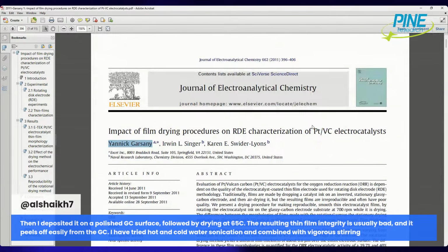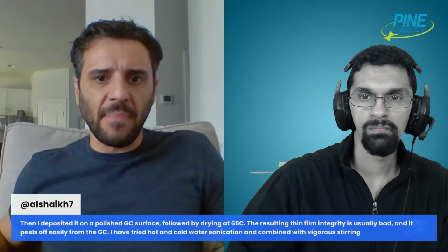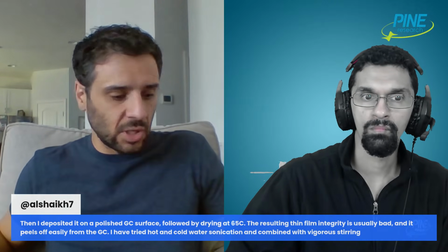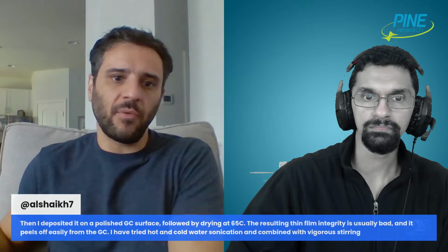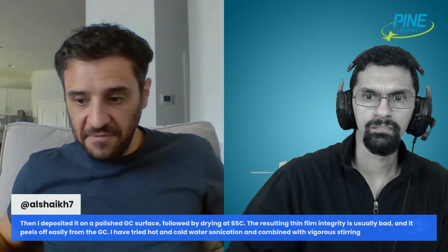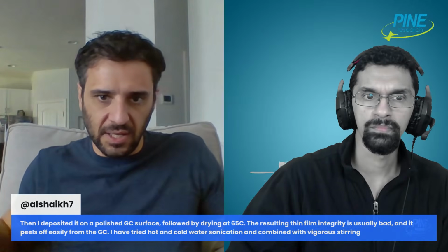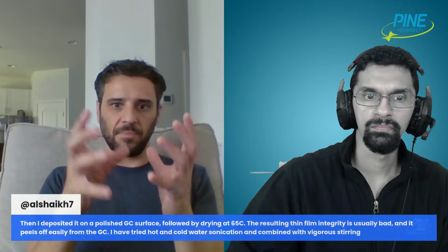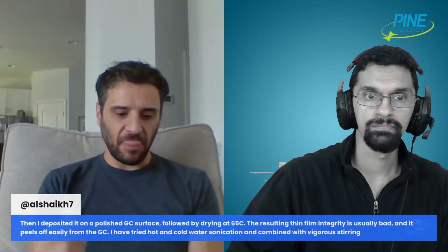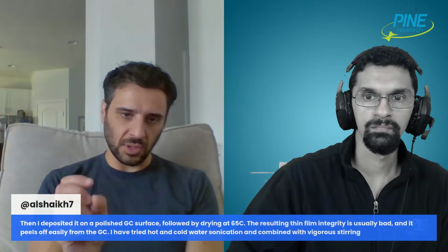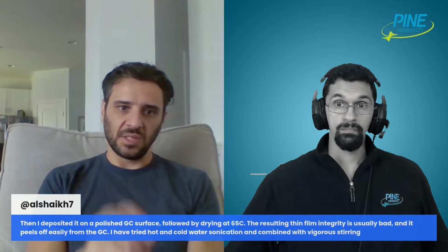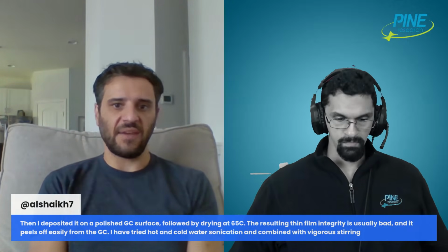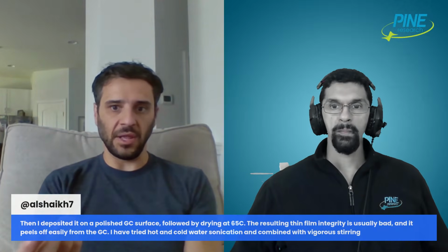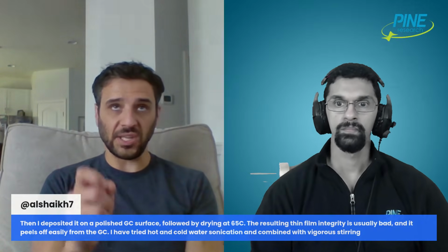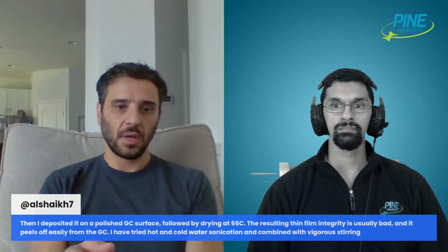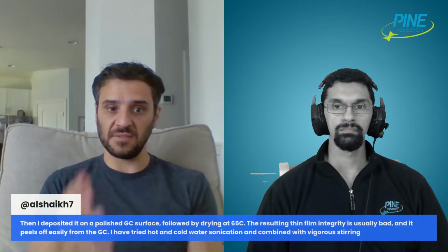Now, I'll stop sharing and just talk through a little bit of this. I mentioned it in my comment back to you, but I'll talk through it. One of the things that you mentioned was that you used 5 weight % Nafion. If that's what you use, you just use some of that stock solution that they usually sell. At least when I was in graduate school, they get little containers of stock solution of 5 weight % Nafion. That's 100 times stronger than you need. So what these films typically consist of is a 100 times diluted Nafion suspension, right? You take 1 milliliter in 100 of that stock solution and create a 0.05 weight % Nafion. It's very dilute. That is the level of Nafion that is typically used in these films.